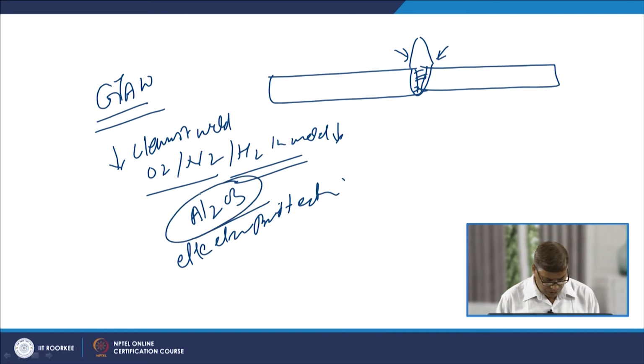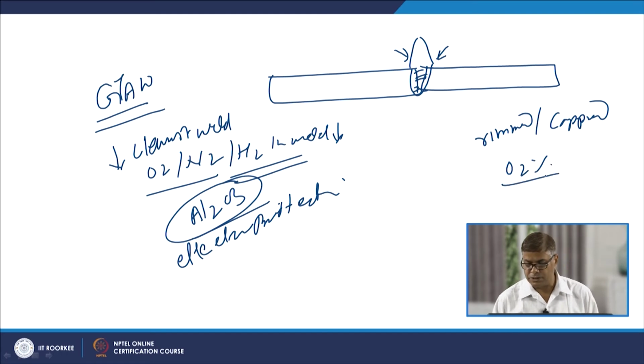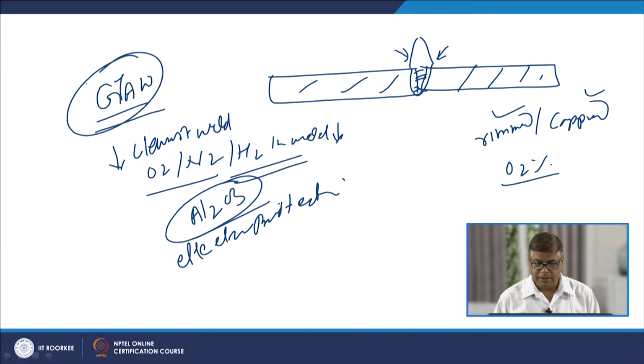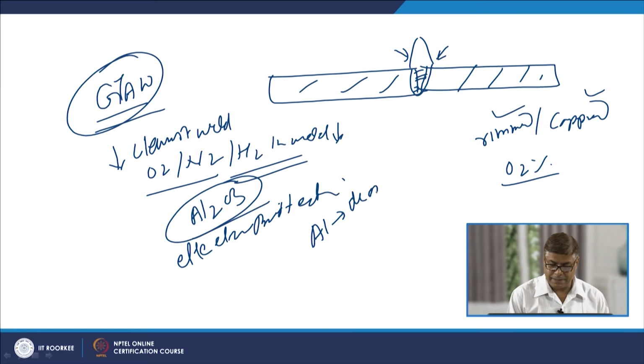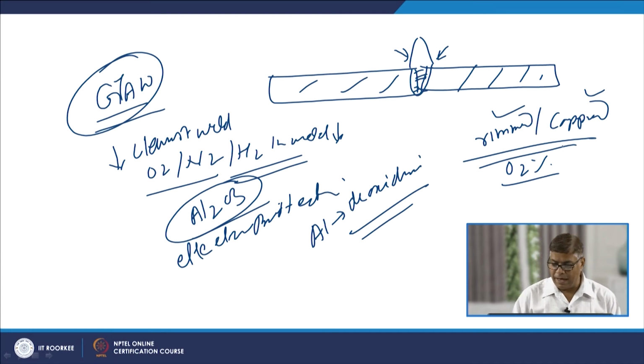So, Al2O3 formation is significantly reduced, and that is why even if the steel is of the rimmed or capped type, where the concentration of oxygen in the steel sheet itself is higher, steel sheet of the rimmed or capped type can also be welded effectively using the GTAW process, and the aluminum in those cases does not create much problem; rather, the aluminum present acts as a deoxidizer. So, in case of the GTAW, aluminized steels do not create much problem.